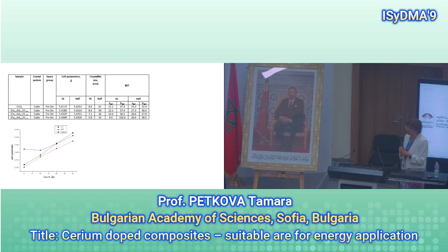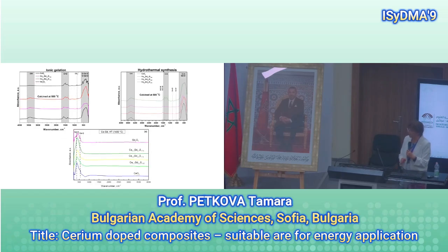From the experimental data of the HIXRD study, we calculated cell parameters, crystal system, and space group. As you see, the space group and the crystal system remain stable cubic, and the cell parameter increases almost regularly with gadolinium content due to the higher size of the gadolinium ion.